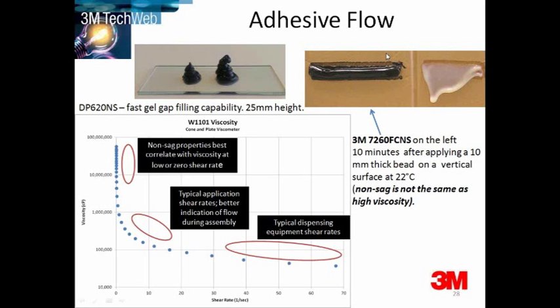After applying the adhesive, ten minutes later there was no sag. So when you apply shear rate, you want good flow characteristics. When you remove the shear rate, this non-sag characteristic — this behavior is thixotropic — can be very, very important if you're applying adhesives on vertical surfaces in certain applications.